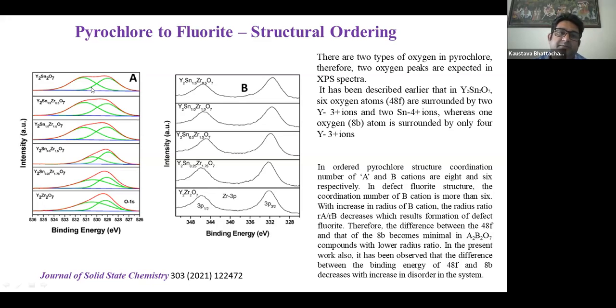But as we dope zirconia, it goes from exactly pyrochlore to a fluorite. A fluorite has both A and B with the same equivalent coordination number of 8. So the coordination number of B increases and that of A decreases, and thereby the difference between the binding energies of these two oxygen atoms also nullifies, and their intensity decreases. That we exactly get from there.